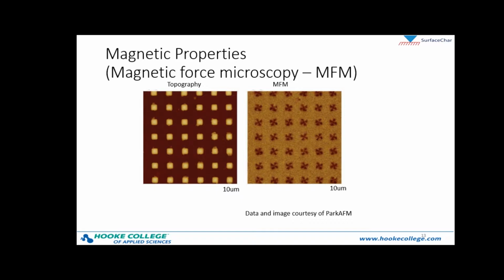In this particular application, a patterned array of magnetic cobalt structures was fabricated and imaged. The topography here on the left shows an array of submicron square dot structures, whereas the MFM image shows magnetic contrast and a very different type of structure associated with its magnetic charges that is obviously unique to the MFM contrast channels.